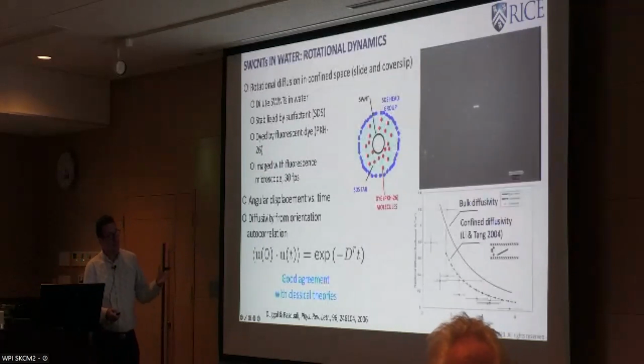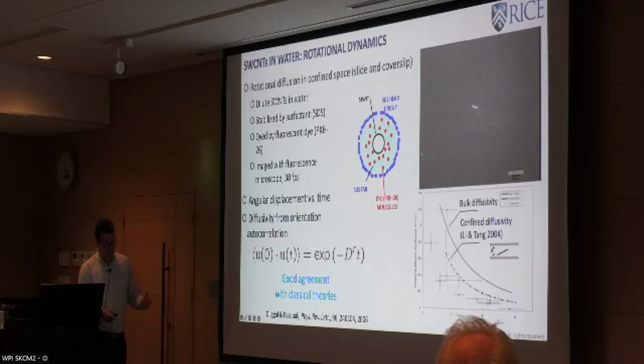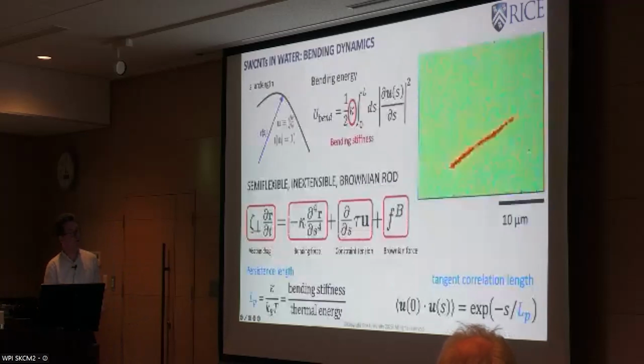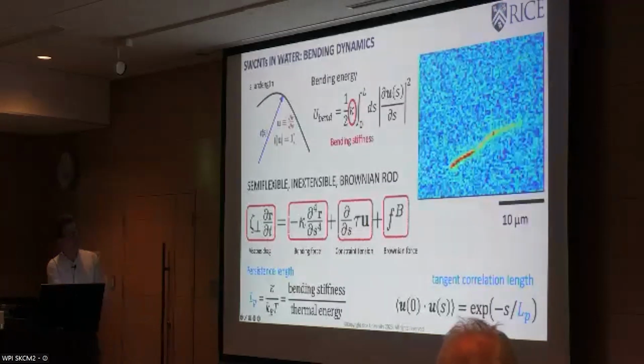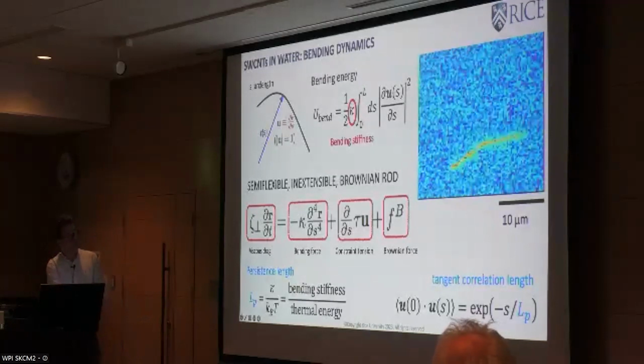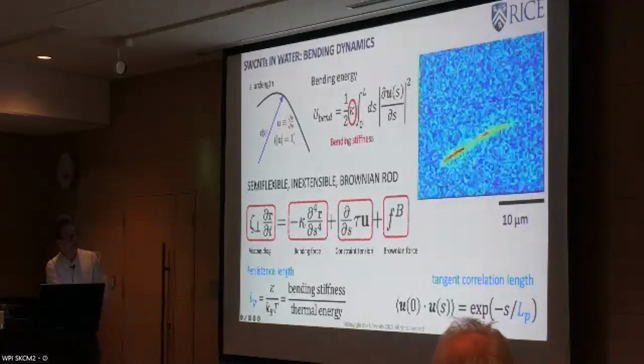So first of all, does this stuff behave like rods? That wasn't clear back in 2000 when we started working on this. And so these are now carbon nanotubes that are being stabilized with a surfactant and are diffusing under Brownian motion. And sure enough, you measure the rotational diffusivity and you apply the classical theories for dilute rods and they work just fine.